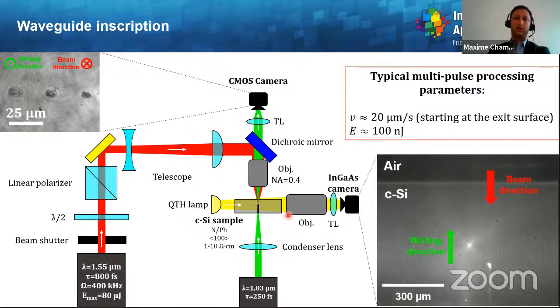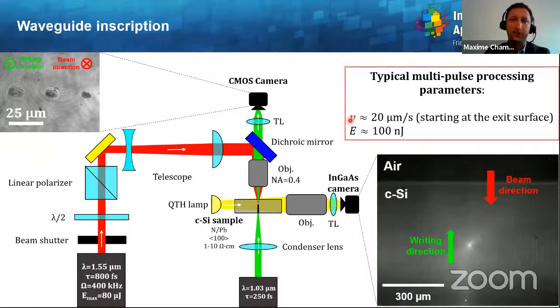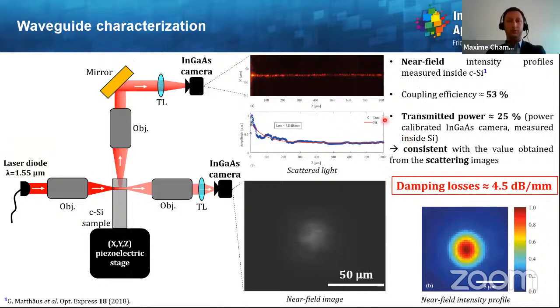And with the first infrared microscope in a transverse way, one can see, I hope it will start, yeah. So the idea is to write the waveguides from the back surface and move the focus towards the laser, to take advantage of the brittleness of the exit surface. The typical processing parameters are a feed speed of 20 micron per second and pulse energy around 100 nanojoules. Concerning the waveguide characterization afterwards, this is done post-mortem.